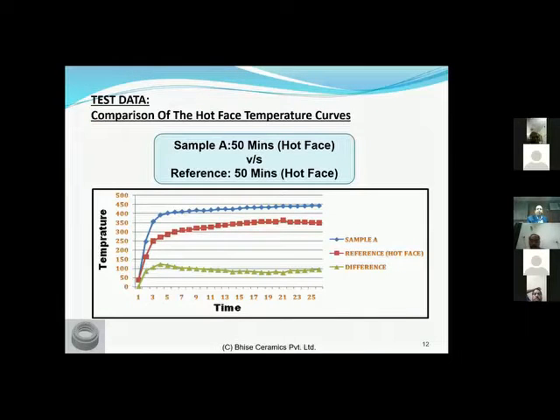This is your first 50-minute reading, where the red is the reference piece with no coating applied. The blue is the sample coating. You can see that after 50 minutes, there is almost a difference of 100 degrees, which means the hot face of the sample with the coating, as an impedance preventing the heat from going across the barrier, ended up being at a higher temperature because the heat did the work of warming up the base plate.